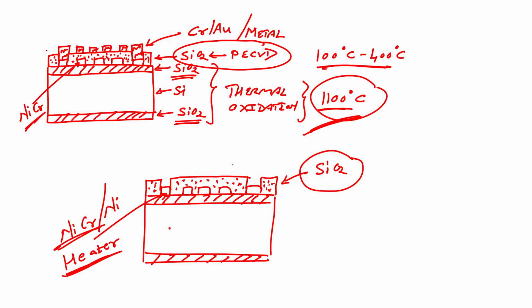Because if I use thermal oxidation for growing this silicon dioxide, then my temperature is around 1100 degree centigrade, and at that temperature the material below it, that is the material below silicon dioxide, which is my nichrome or nickel for my micro heater, should withstand. Now, if it cannot withstand, then I will not get the heater, it will melt, and that will create a problem.